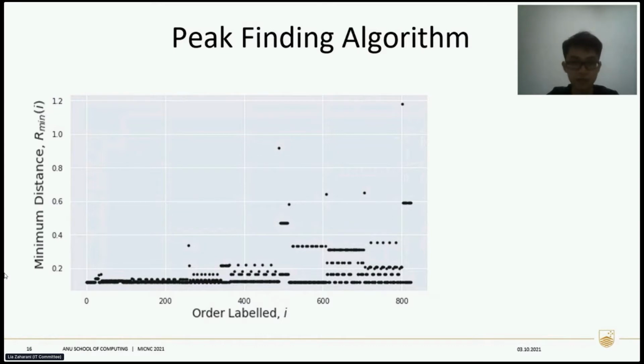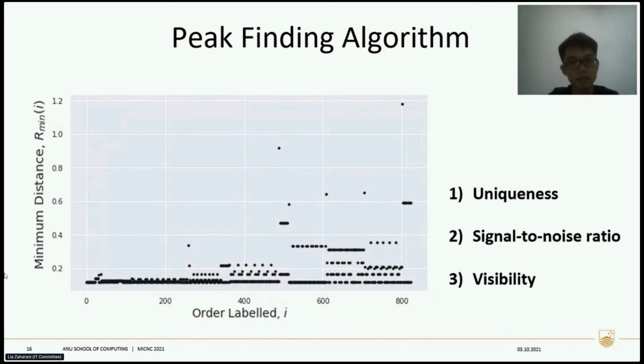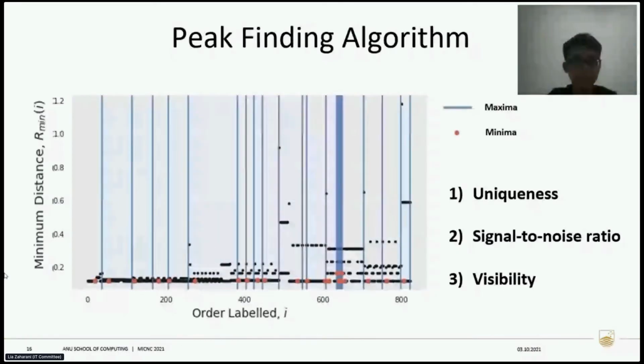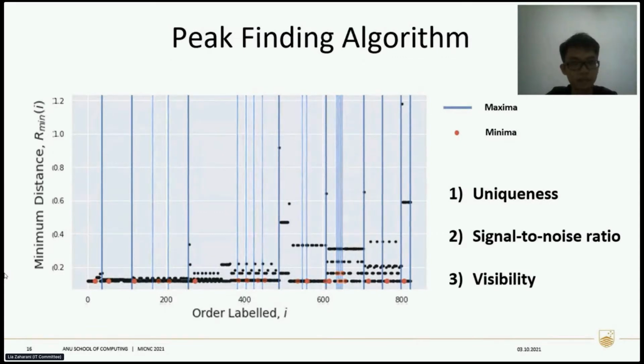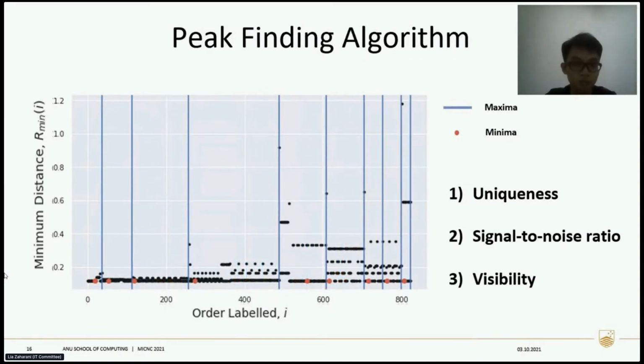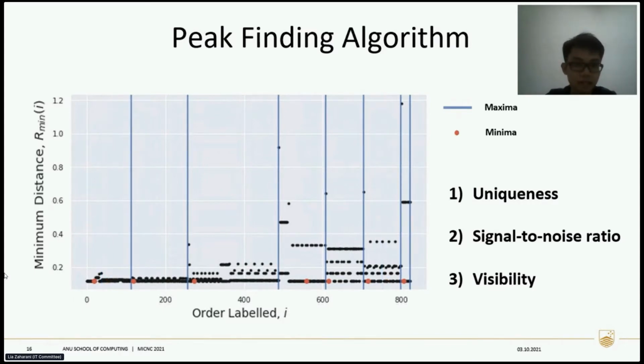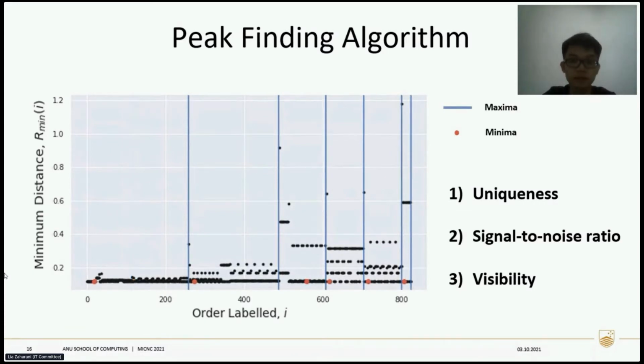So we devised an algorithm specifically to find the peaks in ILS distance plots. And here are the three criteria that a sample needs to satisfy in order to be identified as a peak. Firstly, the peak has to be a unique maximum within a minimum size range of a cluster. Secondly, the signal-to-noise ratio of the peak has to exceed a threshold. And lastly, the peak also needs to exceed a threshold that ensures its visibility to the human eye. These parameters could be tuned to vary the sensitivity of the algorithm, although we are currently setting it to mimic the decision of a human expert.